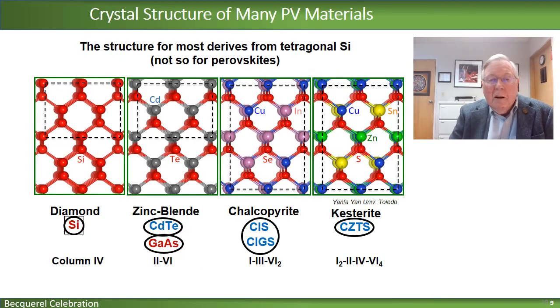And those three are the thin film solar cells I'd like to say a little more about. First of all, I'd like to point out that there's kind of an orderly progression for many of the thin film solar cells, not including the perovskites, where we start with a diamond or a silicon structure, 4 nearest neighbors, and then half are replaced with cadmium and half with tellurium for that material, and going on from there. A quarter with copper, a quarter with indium, and half with selenium for CIS. And then a step further with 4 materials in an orderly pattern for what we call the kesterite cells.